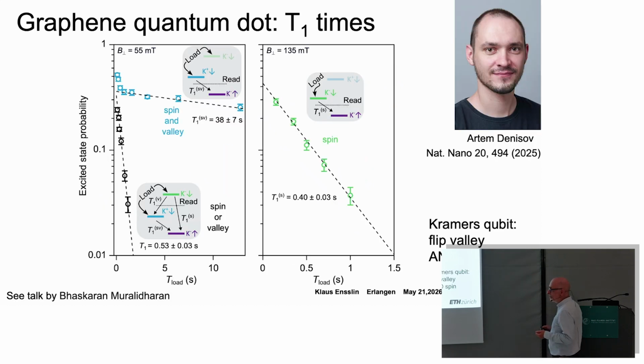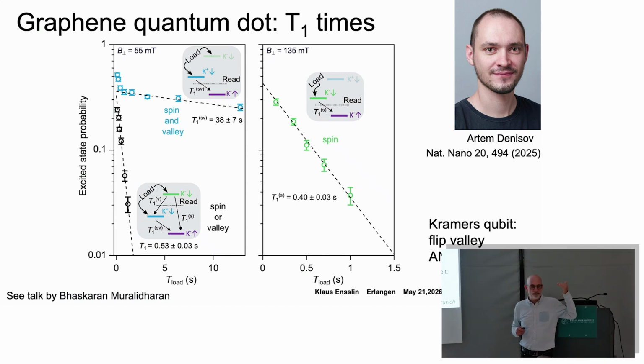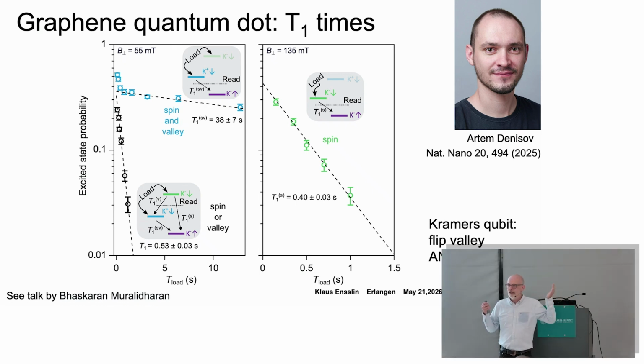So let's now go to the regime where we flip spin and valley. So here are all kinds of lifetimes. This is the spin lifetime. This is the spin or valley lifetime. This is the most important one. This is close to zero magnetic field where you have to flip spin and valley, and it's 38 seconds. Actually, meanwhile, they live so long that we can't measure it anymore. So what we have found is that it is super hard to flip the valley. Actually, now you have a qubit with an infinite lifetime.